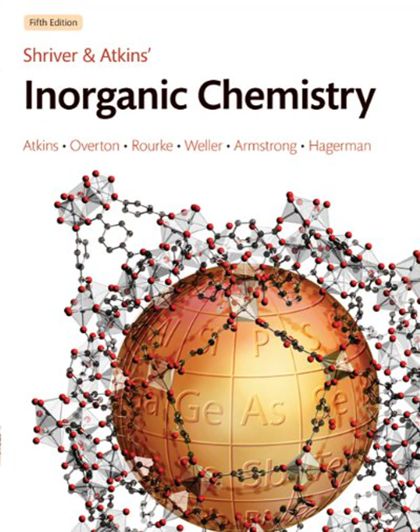Hydroformylation adds CO and H2 across an alkene double bond to make aldehydes, which often get turned into alcohols for plastics and detergents. It uses cobalt or rhodium catalysts, and ligands can steer the reaction towards linear or branched products. And the Wacker process? That turns ethene into acetaldehyde. Uses palladium chloride, but the clever part is using copper to continuously reoxidize the palladium back to its active state, a classic example of coupling catalytic cycles.